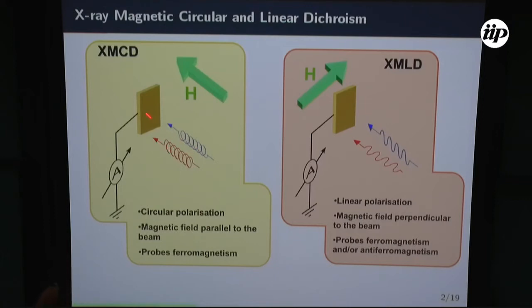When you illuminate with circular polarization, applying a magnetic field along the X-ray beam, this gives you that information that I mentioned on the previous slide, the magnetic moment, orbital and spin. You can do element-sensitive hysteresis, for example, turning on the maximum of the dichroism and changing the magnetic field. You can make element-sensitive anisotropy, measuring dichroism for several angles in a thin layer, epitaxial layer, or single crystal.